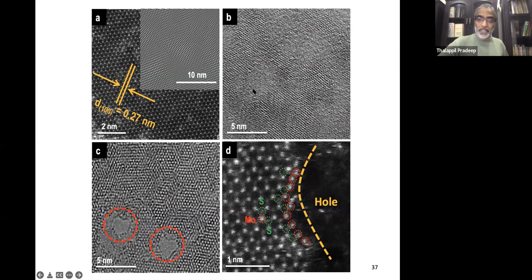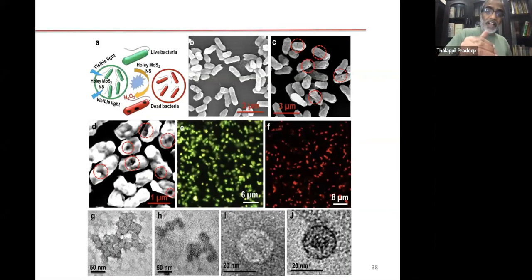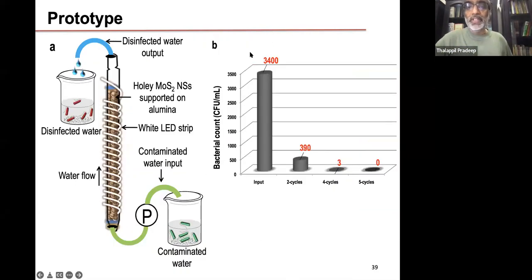holes less than about 2 nanometers, and the surface is expanded or imaged better. And in these high resolution images on this molybdenum sulfide sheet, you see these holes are composed of molybdenum to a large extent. Sulfur is not present. Such molybdenum rich sheets, when you irradiate with sunlight in presence of water, you produce hydrogen peroxide, and they destroy bacteria, and the bacteria get killed, viruses get killed, and you can create clean water with the bacterial content of this passing through such a device.